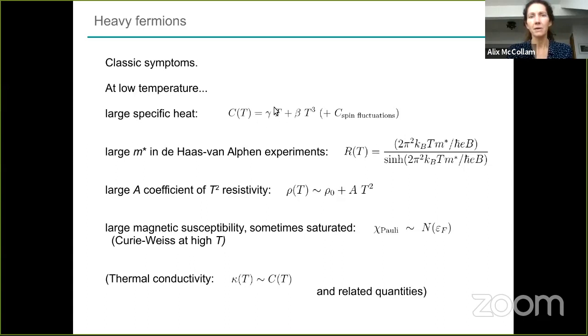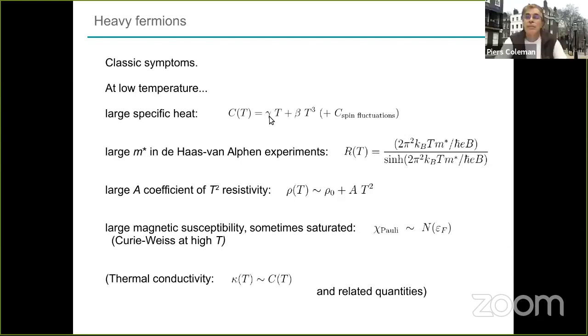So this is the expression for the specific heat, where gamma is the low temperature electronic contribution, and this would be a high temperature contribution. There's also typically in a lot of the heavy fermion materials a contribution from spin fluctuations, but at low temperature we usually see a strongly enhanced gamma coefficient on the specific heat. In de Haas van Alphen and other quantum oscillation experiments, we see a large effective mass. So this is directly probing the effective mass on the Fermi surface.